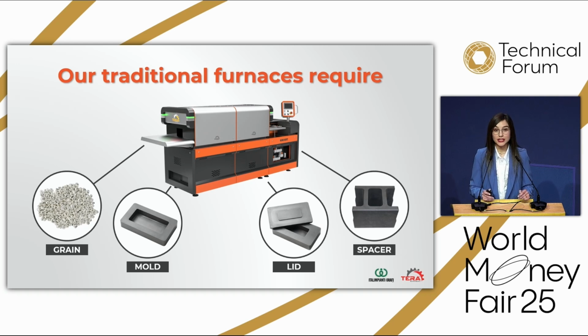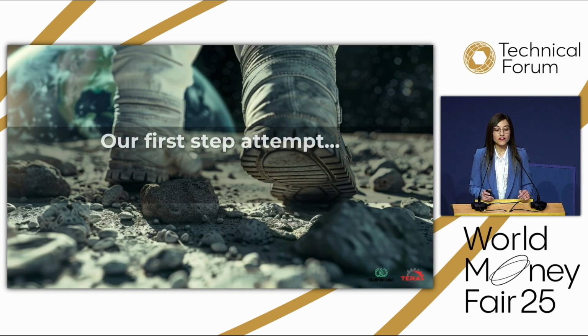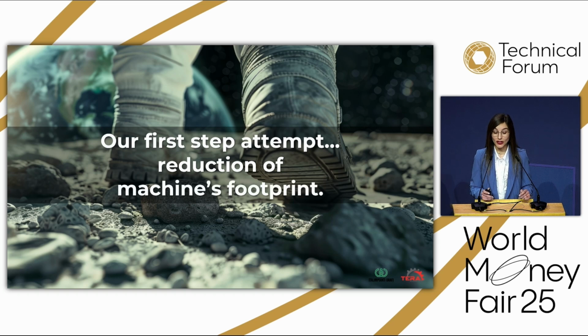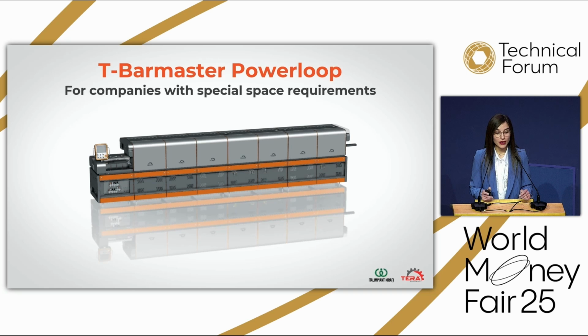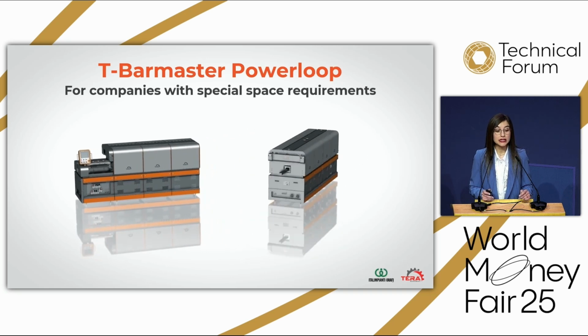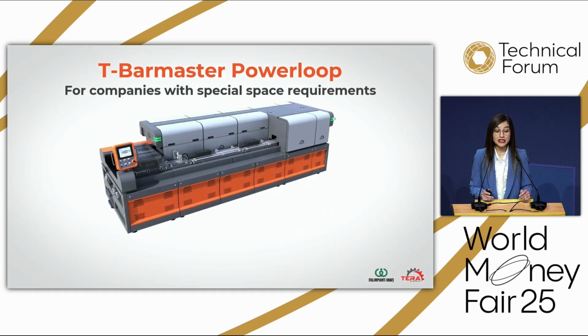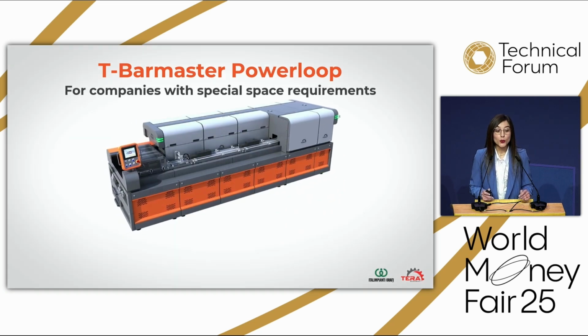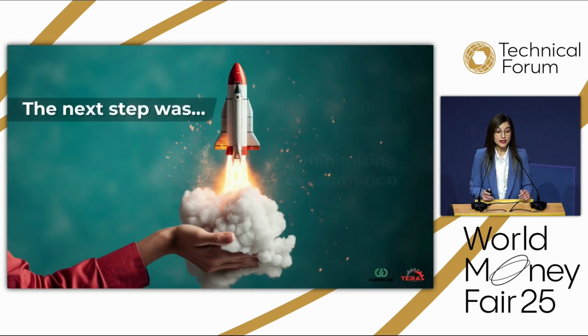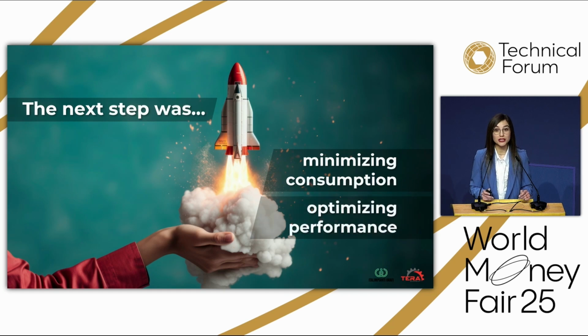The traditional version of T-Bar Master requires the casting of precious metal grains and involves the use of ingot molds with lids and graphite spacers. So, the first real attempt to innovate the T-Bar Master from a 5.0 perspective primarily focuses on reducing the overall machine's footprint and is embodied in the T-Bar Master power loop. As you can see, unlike standard versions, this model does not develop lengthwise, but is configured as a closed loop. In fact, we were able to reduce the overall footprint of the machine by 45% compared to the traditional equivalent T-Bar Master. The next step was to focus on minimizing consumption and optimizing performance.